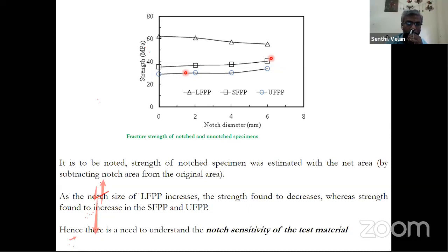The net area is used to be considered for your strength capability, by subtracting the notch area. So we need to really bother about this notch sensitivity. That means when there is some discontinuity like a hole in your material, you will be able to see that it does not always deteriorate. Sometimes it will help also. When the materials sufficiently have some viscous component, it helps. When the viscous component is relatively very small, then it is not going to help. If you look into this long fiber reinforced one, it is deteriorating with the larger diameter. Whereas this one is showing improvement.